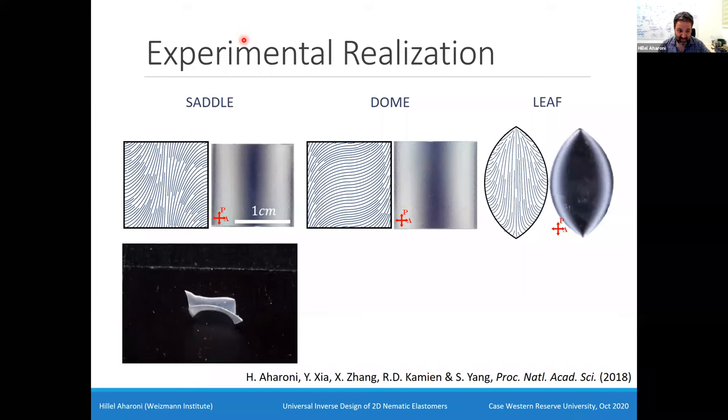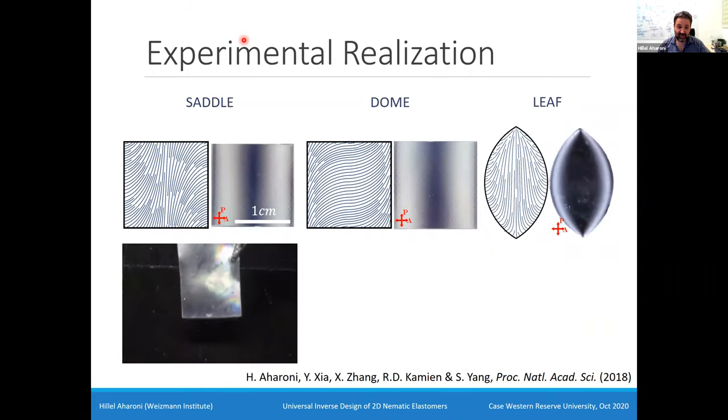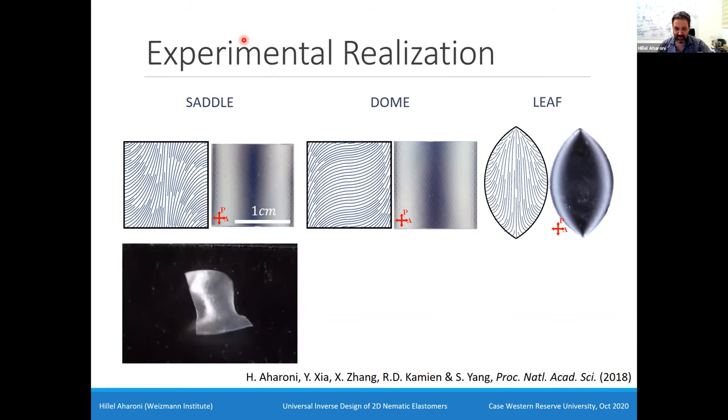Now this is the video. Let me run the video. It dances a little bit because the hot plate is hotter than away from the hot plate. So it's not a perfect saddle. As you pick it up from the hot plate, this is video in real time, it's flat. As you put it back on the hot plate, it goes back into being a saddle. And again, if this was constant temperature, then it would just take the saddle shape and stay.